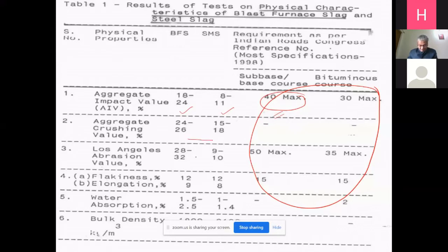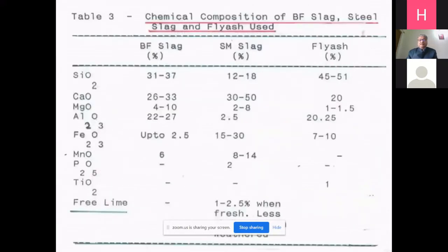Similarly, crushing value, Los Angeles abrasion value, flakiness, elongation, water absorption, and bulk density. In everything, it is coming out to be fairly good, and that is why this was done. Then the chemical composition of blast furnace slag, steel slag, and fly ash used. You can see here, mainly it has silica,